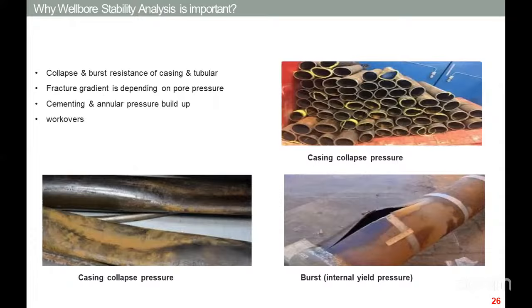I know one company that used a low grade well just to cut the cost. And after they drilled, we found some layer producing more than 10,000 barrels in the test. And after we went for the casing and put it into production, we could not enter the well because the whole hole had collapsed from South Gharib, the salt of the Gulf of Suez, and we lost the well. This is just a small problem. Cost optimization is not valid in everything. You should know the stresses, you should know the problem. After that, you choose the proper way to deal with it.